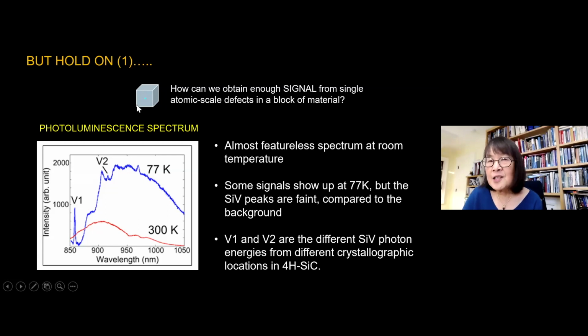But as indicated symbolically here, how can we possibly attain enough signal from a single atomic scale defect that's buried someplace in a block of material? And indeed, if I try to excite a block of material and take a look at the resulting photoluminescence spectrum that this emits, at room temperature, what I get is an almost featureless spectrum that basically tells me very little to nothing about the local environment.